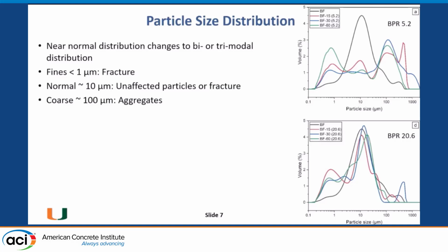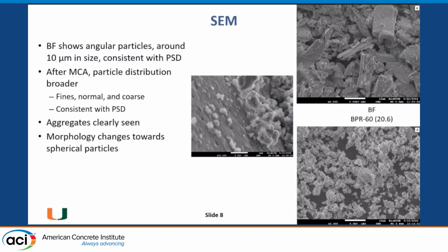The explanation that I have, at least at this point, is that the fines, which are typically less than 1 micron, are of course created by fracture. The particles around 10 microns in size are either unaffected particles or particles created from fracture of yet larger particles. And the particles which are about 100 microns in size, these presumably are some sort of aggregates, agglomerates, etc.